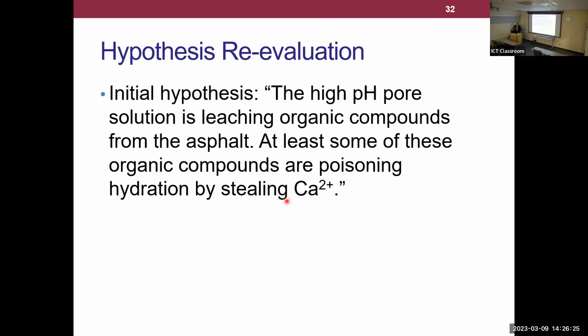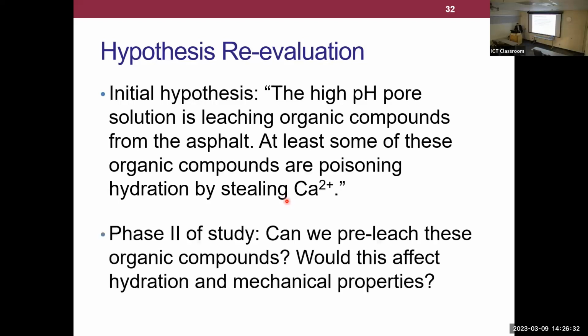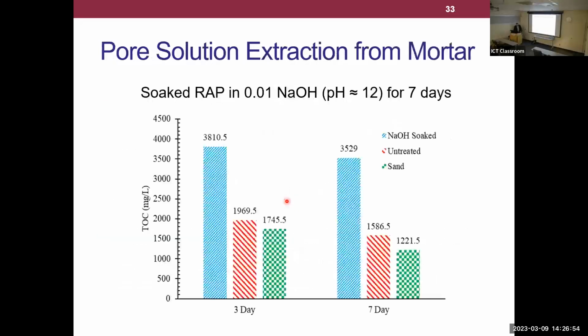Now we have an idea of what this mechanism is, why we might be getting this larger, more porous ITZ. So our next question is, can we pre-soak the RAP, leach those compounds, and call it a day? Maybe we'll get better performance. That's what we tried next. We took all of our RAP, soaked it in a high pH solution, again sodium hydroxide, washed it, and then mixed it into our concrete or mortar. And it didn't work. Unfortunately, that hypothesis did not prove right, because what we actually saw is that the pre-soaked RAP gave us a lot more organic compounds than the RAP that we never treated in the first place.